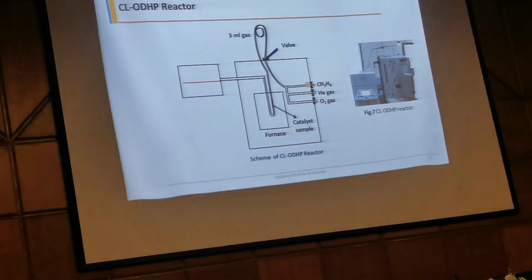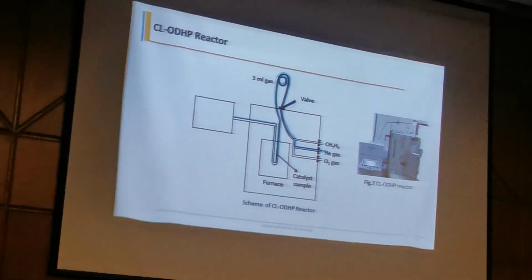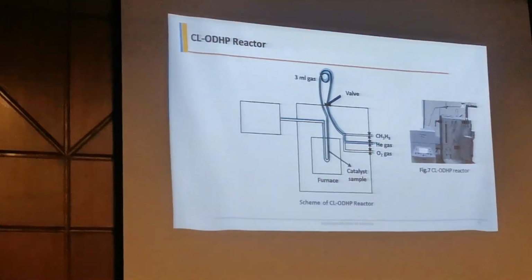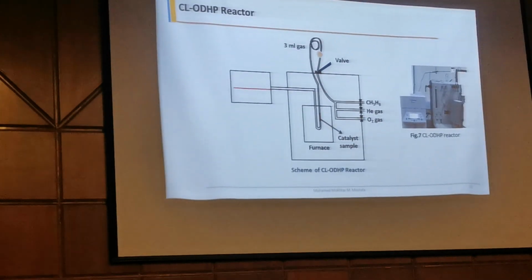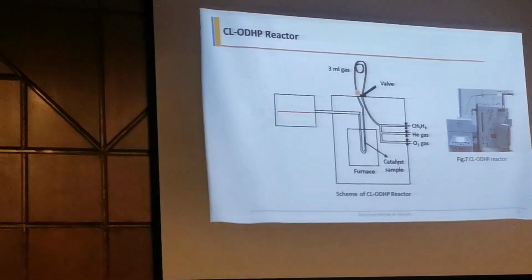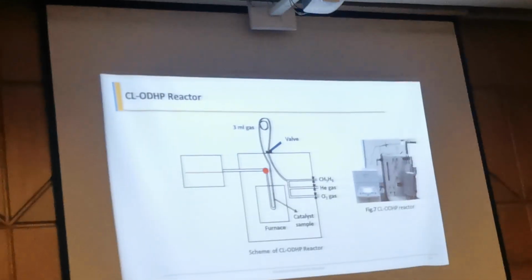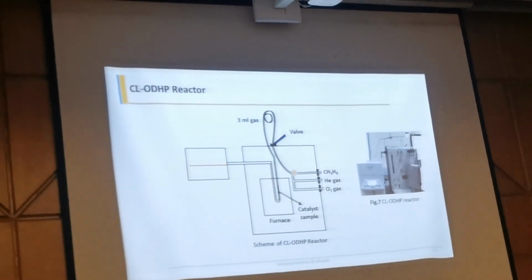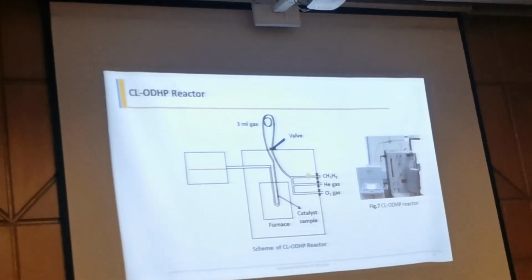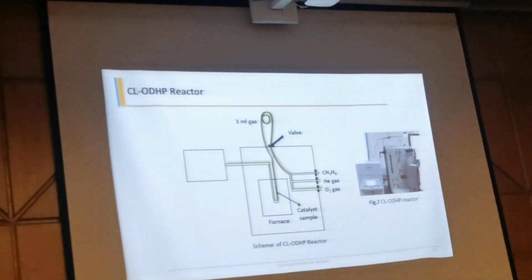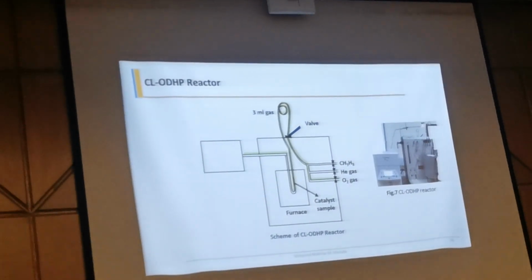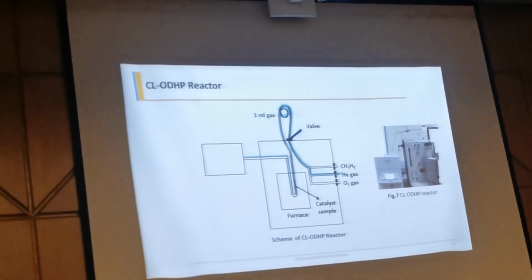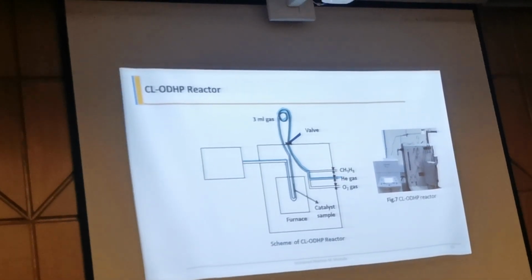directly. Then you rewash the catalyst with helium and repeat the experiment again and again until you remove all the oxygen from the surface. Every time you do a pulse, you follow what is going on. At the end, you can pass oxygen to reoxidize your catalyst, then rewash, so you have the oxide form, and repeat the experiment. It's called the transient pulse or loop technique.